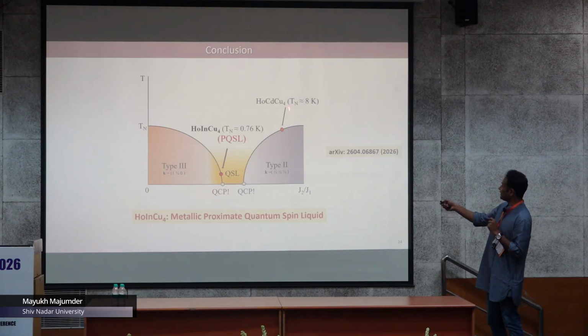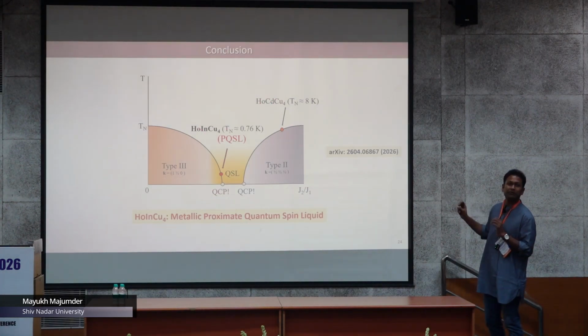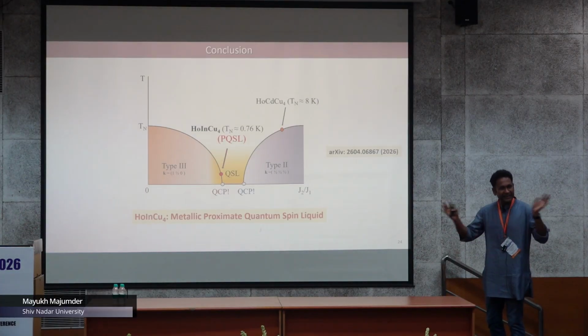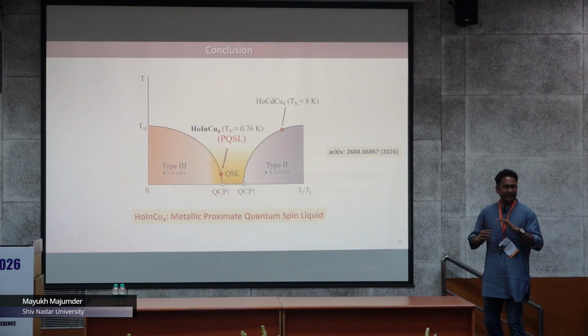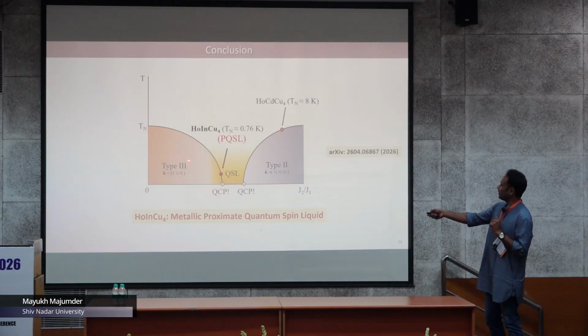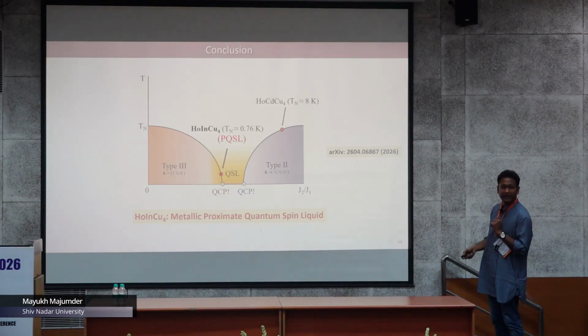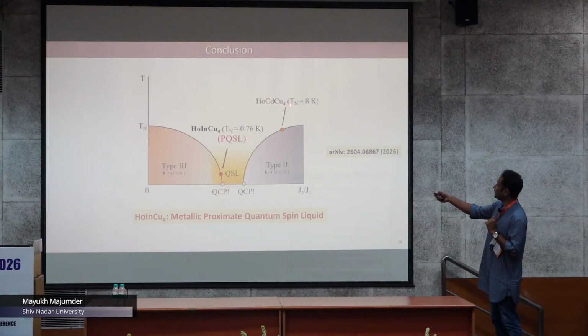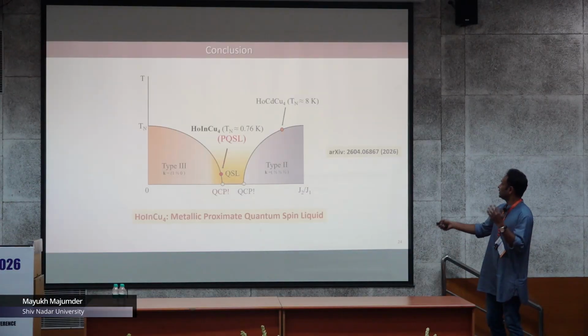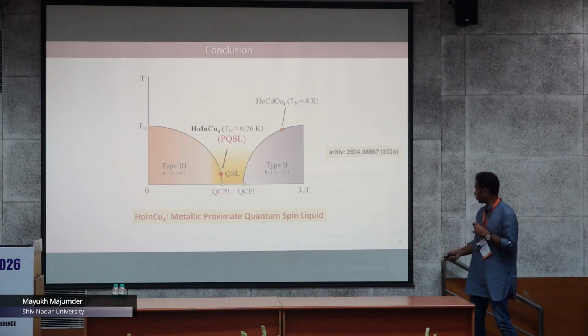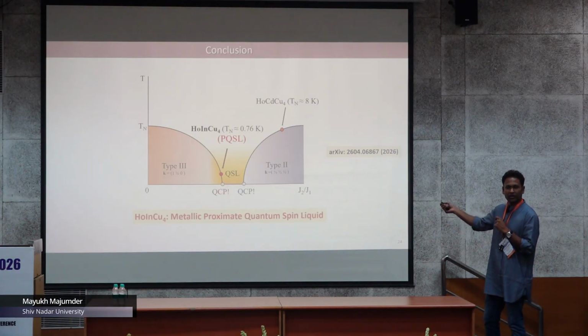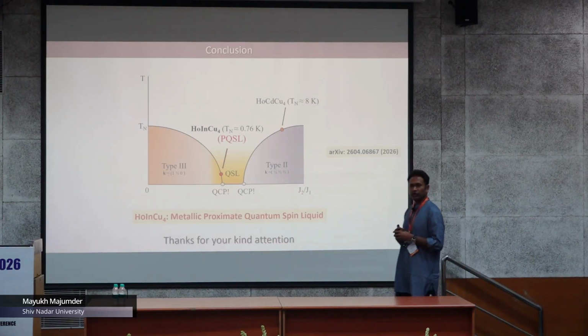And we also studied a compound in the same family, where the indium is replaced by cadmium, which doesn't show any signature of frustration, and it shows complete long range magnetic ordering. This is the type 3 antiferromagnetic ordering for holmium indium copper 4, and this holmium cadmium copper 4 is a type 2 ordering. And again, we do not know whether there will be a QCP, but this is the phase diagram that we proposed. Our paper is on arXiv, and thanks for your kind attention.